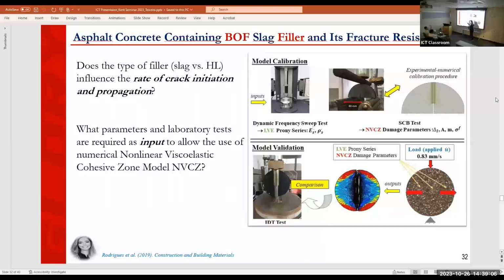She did some frequency sweep tests where we could get master curves of dynamic moduli as a function of frequency. We converted them to the time domain and obtained the Prony series, which was important for the modeling. Then we also did SCB tests to get fracture parameters through a calibration process. Once we had the Prony series, linear viscoelastic properties, and fracture parameters from the model, we could simulate another test, an IDT test, for validation. So let's see the differences that we got.